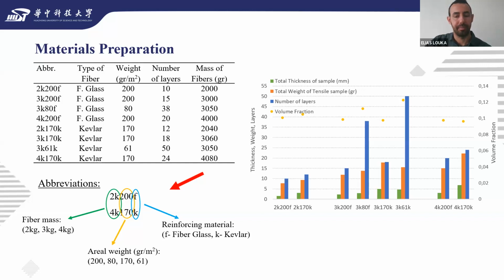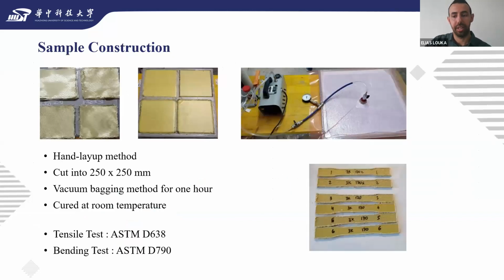About the sample construction, samples were prepared as sheets with multiple internal layers. A hand layup method was used to construct the specimen. First, reinforcing fibers were uniformly cut into 250 by 250 millimeter pieces. The composites were fabricated by using the vacuum bagging method for 1 hour. The samples were then cured at room temperature.